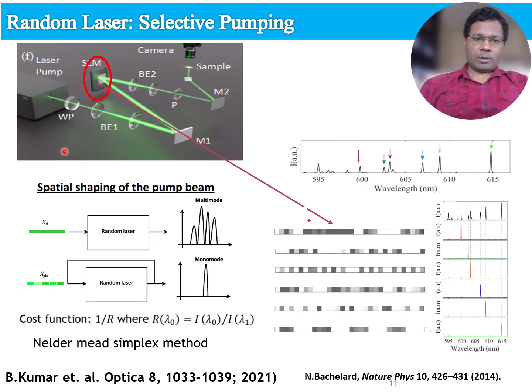We have implemented this iterative optimization method on our sample, and for that we have used this experiment setup where a spatial light modulator is used to modulate the incoming pump beam, and after modulation the pump is imaged on the surface of the sample from the bottom. Our sample is on a substrate of fused silica, which is transparent, so that allows us to pump the sample from the bottom and image it from the top.